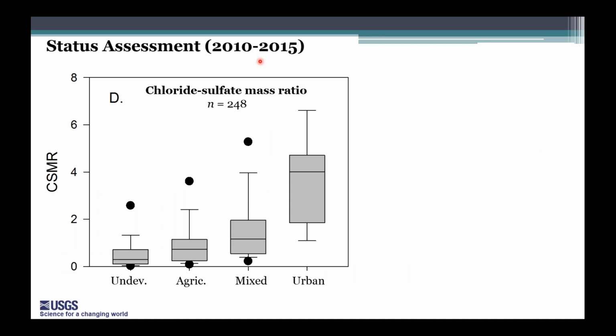The status assessment covered the period 2010 to 2015 to give a better idea of the average chloride to sulfate mass ratio, and approximately 3 times as many sites were included in the status assessment. So as I mentioned earlier, the data requirements are not as stringent, and so we end up picking up a lot of sites and we can describe spatial distributions much better. And we can see that urban sites, in addition to having large increases over the past few decades, also have the highest average chloride to sulfate mass ratio.